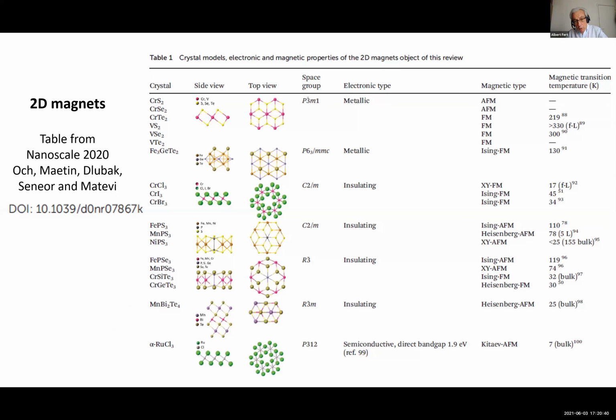A general property, and this is a bottleneck in this field, is at the moment the too low ordering temperature, a consequence of the Mermin-Wagner theorem. Generally all these compounds you can see here have an ordering temperature below room temperature, but it's not desperate. In fact, there are some results that show that this temperature can be enhanced well above room temperature by proximity effect, for example, the record being 400 Kelvin at the moment. So for the moment, the bottleneck is this temperature.